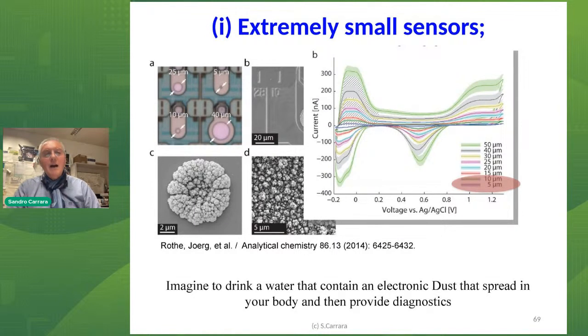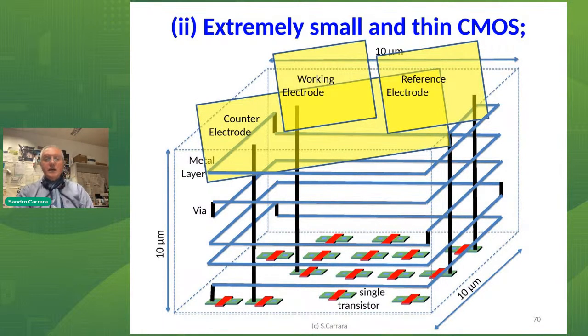Well, my colleague Irleman and his group already published in 2014 this paper in Analytical Chemistry, showing the possibility to reliably measure glucose down to 5 micron electrode size, thanks to nanostructuration with nanoplatinum of the working electrode. You see here the nanoflowers. On the CMOS side, we then need to scale down to 10 micron. On top, we can deposit the platinum or gold electrode in order to realize directly the electrochemical sensor on top of the CMOS die.